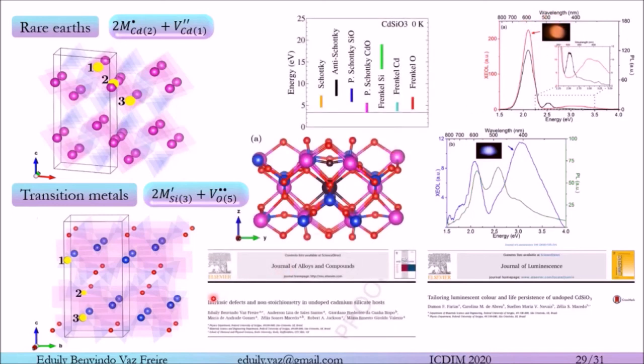In this paper, we found that the least energetic intrinsic defect is the pseudo-Schottky of CdO, formed by cadmium and oxygen vacancies. A very interesting fact is that intrinsic defects and extrinsic defects generate the same vacancies in the matrices. This fact contributes to the idea that intrinsic and extrinsic defects have a common origin, which is the pseudo-Schottky of CdO defects.